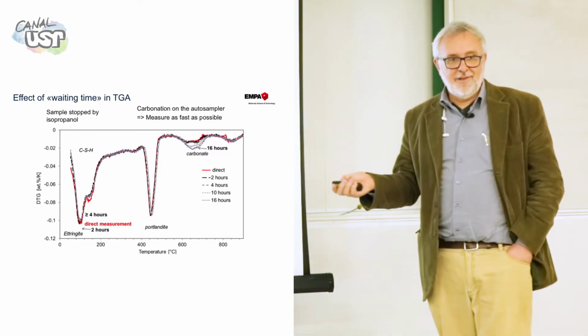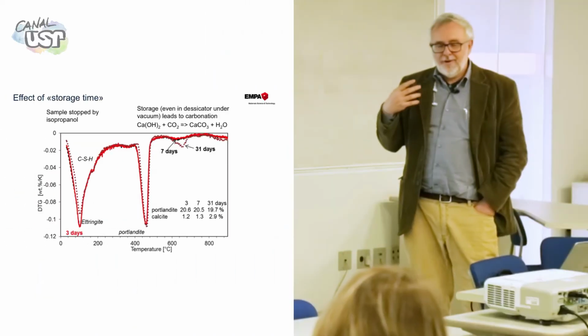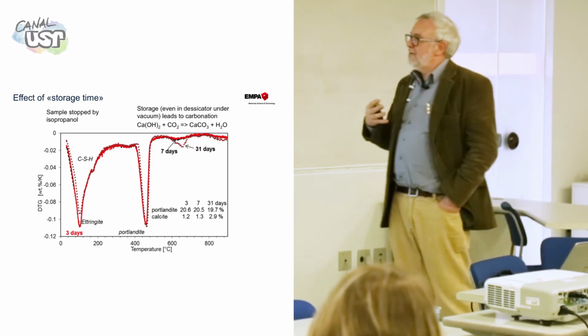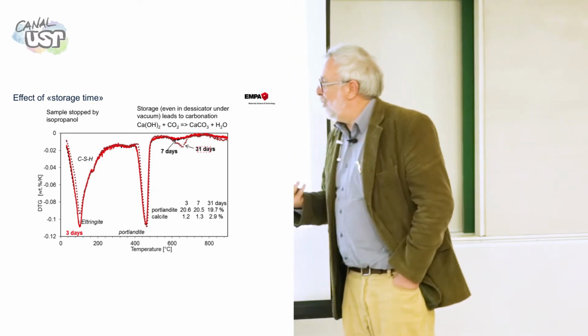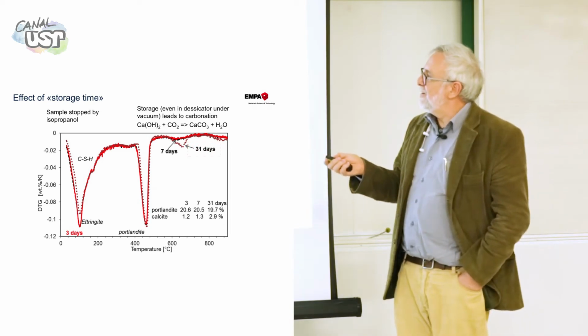This is in the autosampler. That's just to leave. It's like 110 or 120 minutes for each test, so it takes a while. So if you want to store, you grind and you store in a desiccator and you put it in a vacuum and you leave it 31 days, you think it's okay, but it isn't, because your vacuum is not perfect. When you do high vacuum, you are going to destroy it here. You see, you lose ettringite also. So I think the best thing is to do it on the spot.